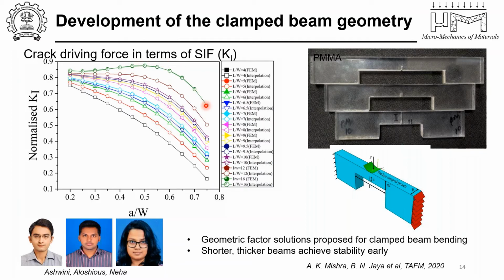So the point is that if the beam aspect ratio increases, then this zone or this region of stable crack growth in fact goes down. The region of stability is reached right at the point of 0.2 for, let's say, L/W of 4, but it is reached only at a point of a/W of about 0.45 or 0.5 for an L/W of 16. So the L/W of 16 is not very useful.